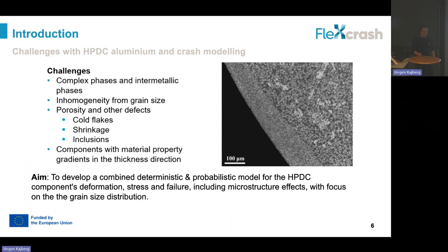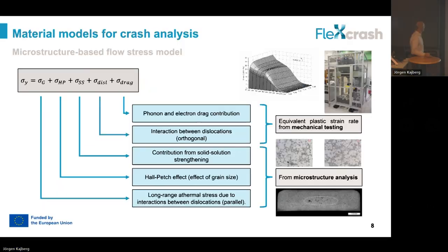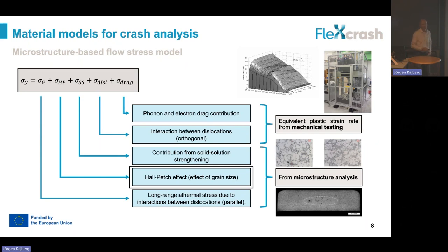And to talk a little bit about how we're going to tackle this, I will hand over to Daniel here. Just to repeat a little bit about the material model, what is that? That's, you can say, a mathematical description of how the material behaves. Usually you have a lot of different phenomena, but in this project, with high pressure die casted material, we will focus especially on the effect of the grain size. As you saw in the picture before, you have quite different grain size on the outer surface of the component and in the center, and this needs to be taken into account. Even if we create a very good physical base model, we will always require material testing. In some cases, it can be a little bit more advanced testing with higher strain rates, but that needs to be included, even if we know the microstructure.